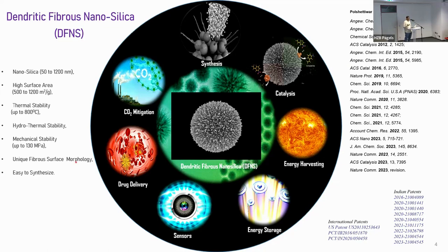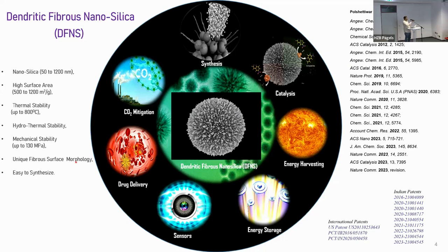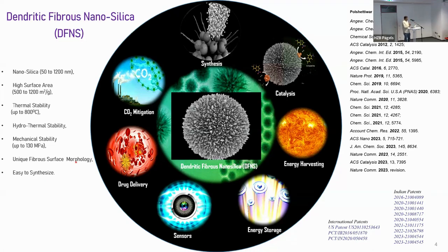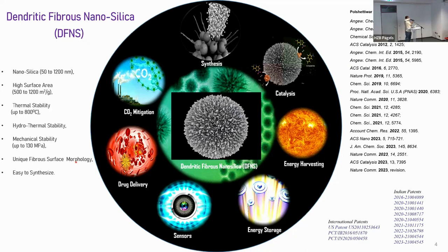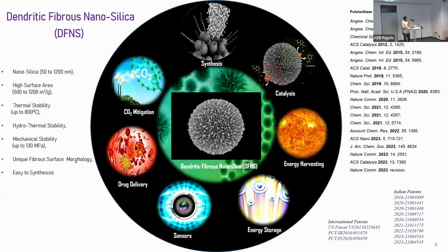Right? Most of the high surface area materials, look at MOF or SBA-15 or MCM-41, those are all pores. You have one entry and one exit, which has an issue in terms of the diffusion of the reactant and the product. Here, it's more like an open structure. It's like a marigold flower. So that means reactants can diffuse in from different positions and products can diffuse out, right? And that makes the process very sustainable. And then it's easy to synthesize, right? And we were able to even upscale this from milligram to now up to 100 gram scale.